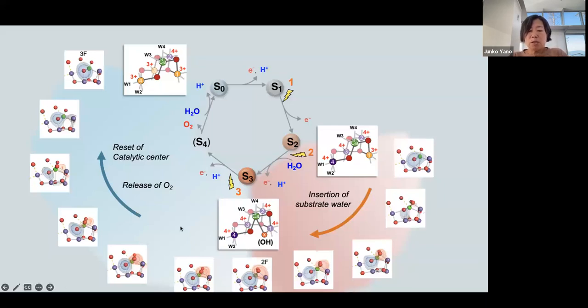So what's next? We haven't really seen the exact structure or chemical state when O-O bond formation occurs or subsequent steps. So, of course, one effort is to improve the crystallography resolution much more. Currently, it's getting close to 2.0 angstrom, but we need to go beyond that. At the same time, we can do a different type of spectroscopy, which is absorption spectroscopy, using XFELs, that gives us a more detailed electronic structure, as well as local geometry or atomic distance changes of the metal cluster.